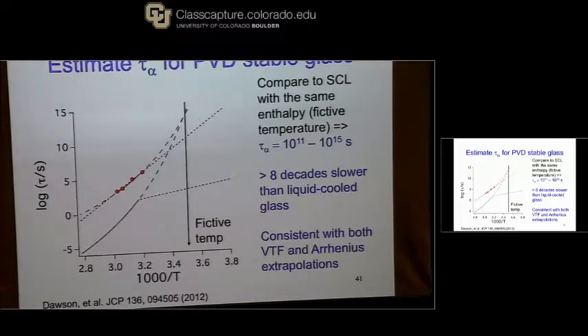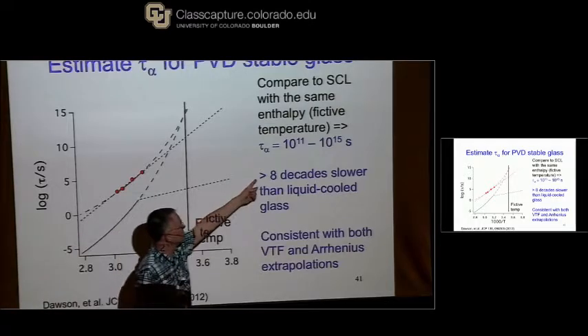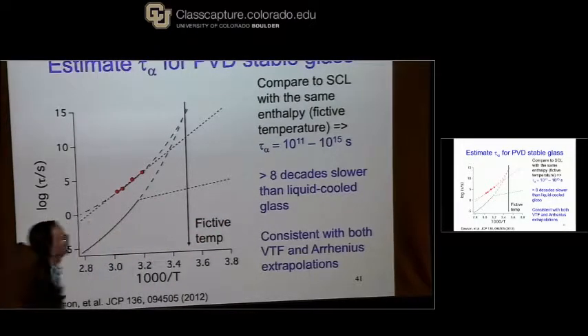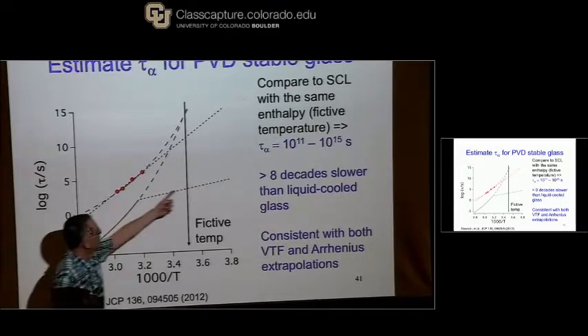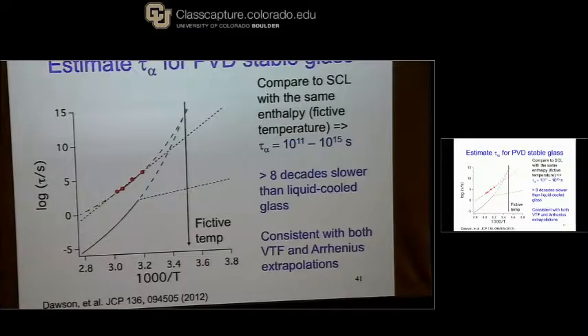The alpha relaxation time is long, but if some experimentalist, some clever simulator can come out with an idea for how to do this extrapolation better, that would be really helpful. Okay, because we'd really like to be able to say something more precise about what our alpha relaxation times are at low temperatures. But the good news is they're big. We would estimate at least 10 to the 8th times longer than the liquid cooled glass at that same temperature. Okay? So these are quite kinetically stable materials.